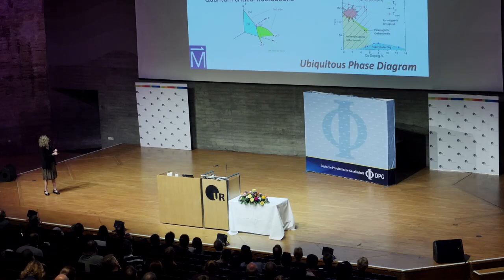up here, above this green band, if you look down on the lattice, it's tetragonal, it's square. But the electrons at 175 degrees, these are like cuprate superconductors, way above 175 degrees, the electrons start forming these sausages or whatever, cigars, whatever your favorite is. And they actually go into C2 symmetry, and they break the symmetry of the underlying lattice. And this is the key to all these correlated electrons, that the electron-electron correlations are stronger than the electron-lattice correlation. That's the definition. And there's many other things: the pseudogap, the heavy electrons, things striping up.